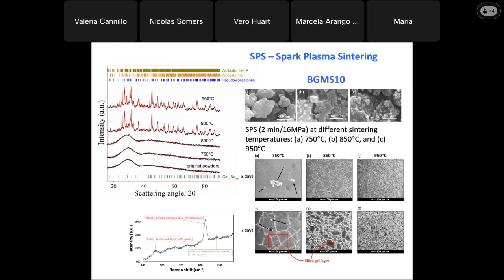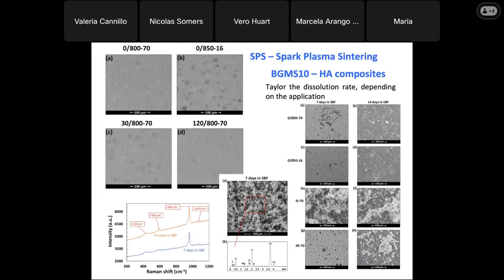So you can see products obtained with BGMS10. And of course, depending on the processing parameters, some crystallization was obtained in some samples, while some other samples were completely amorphous. Also in this case, the in vitro results were very good. And we also produced composites with hydroxyapatite, and this was done to tailor the dissolution rate because, as you know, the dissolution rate of bioactive glasses is much faster than that of hydroxyapatite, so you can tune the dissolution rate by building a composite. And also in this case, the tests in SBF were encouraging.